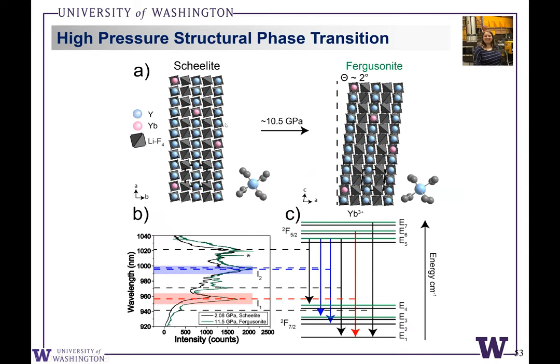There's a really interesting structural phase transition of these materials. We start with a scheelite phase, which has tetragonal symmetry and S4 point group symmetry. And under high pressure conditions, we can change the phase of this yttrium lithium fluoride host, and also the point group symmetry. And as a function of crystal field conditions, the pressure will shift the intercrystal field energies as a function of pressure, just based off of the local microenvironment changing around the lanthanide ion.